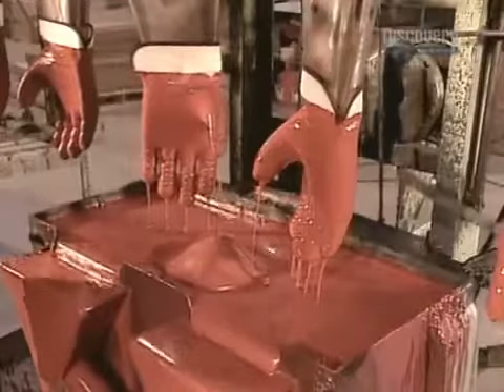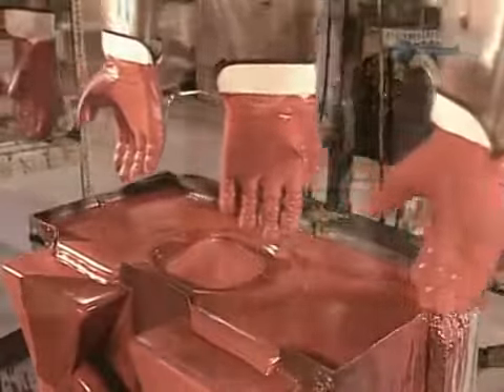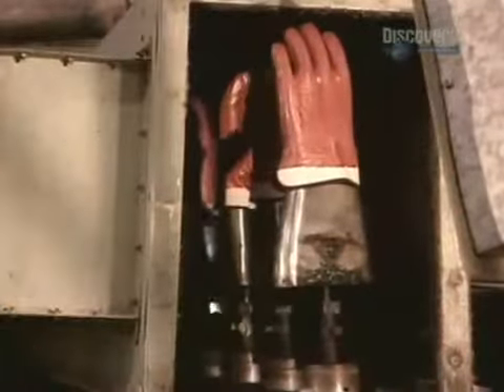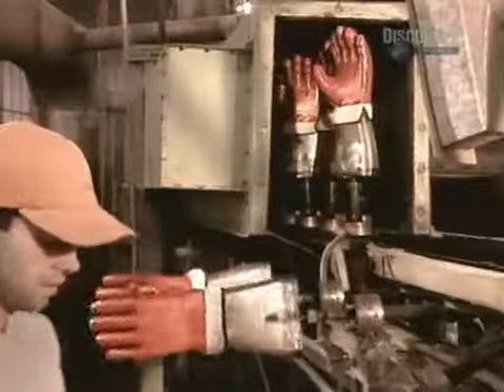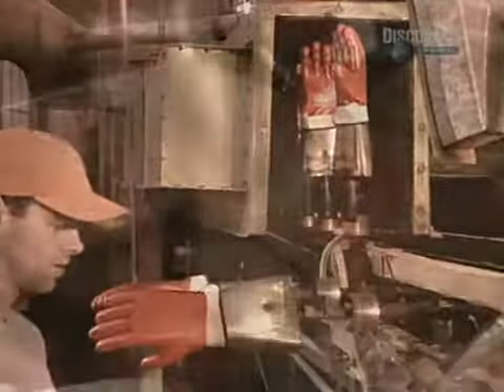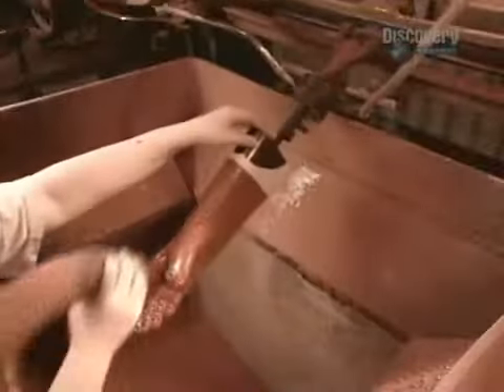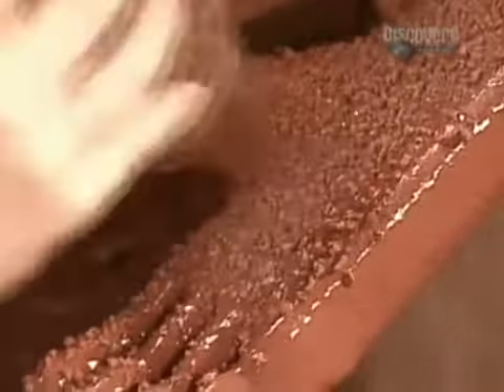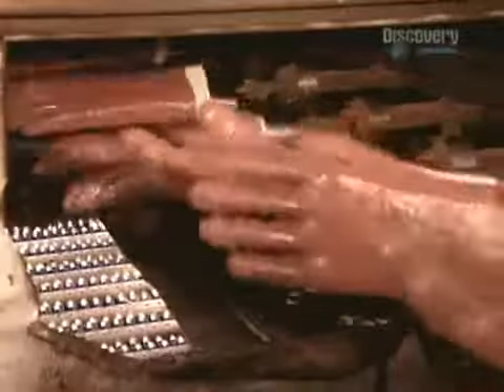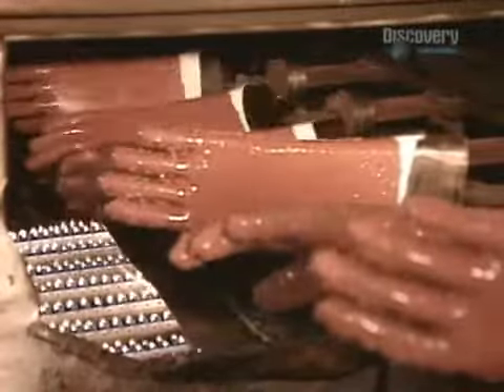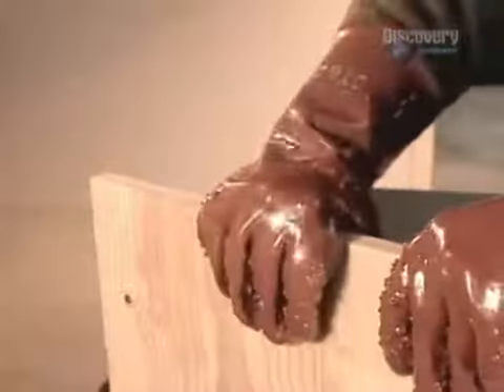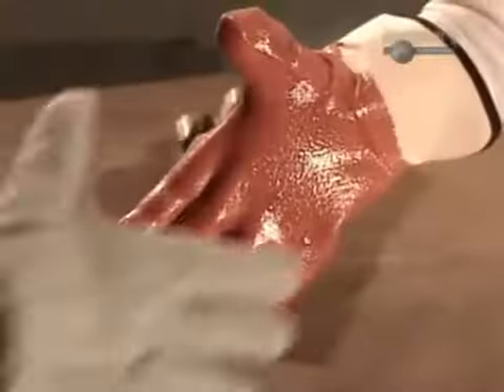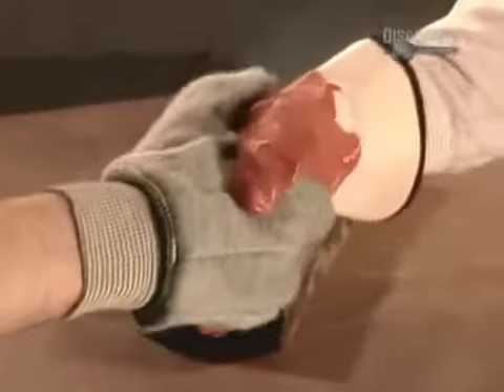After a second coat, the gloves pass through a propane-fired furnace for about 20 minutes at 190 degrees Celsius, then through a cooling chamber for 5 minutes. For glove models with extra strong grip, PVC chips are blown onto the first coat of PVC while it's still wet. When the gloves go through the furnace, the heat embeds the chips. After cooling, the gloves are dried and cured and ready to handle a hard day's work.